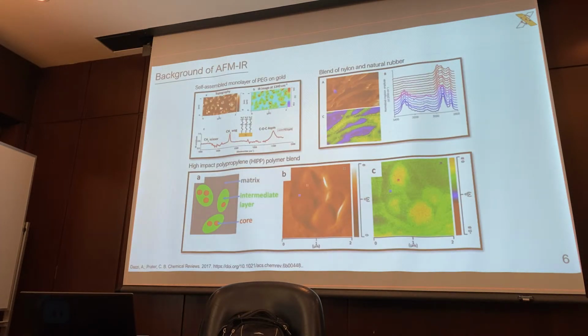So, for instance, we've seen AFMIR used, and this is more references from around the 2016 area. Some people looked at self-assembled monolayers of polyethylene glycol on gold, blends of nylon blended with natural rubber. And they're able to really define where each of these particular materials resided. Here we have high-impact polypropylene. That's another polymer blend where they were able to identify a core within this intermediate layer, which is then controlled in this matrix formation here.